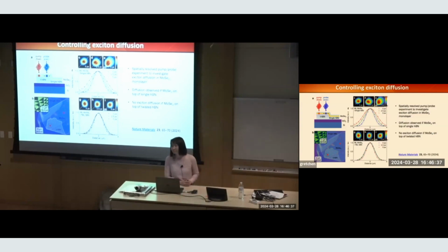When are you mostly using emission spectroscopy? We do use emission and absorption. What's the difference is that emission is a two-step process. It has to absorb first, and oftentimes they decay to some lower energy states and then emit. For example, I told you about the intralayer exciton, right? The intralayer exciton has very large absorption, 5%, but the interlayer is 20 times weaker than that. So on a really good, well-prepared sample, you would only see the interlayer exciton in luminescence. You will only see the intralayer exciton in absorption. They measure different groups of excitons in the material.